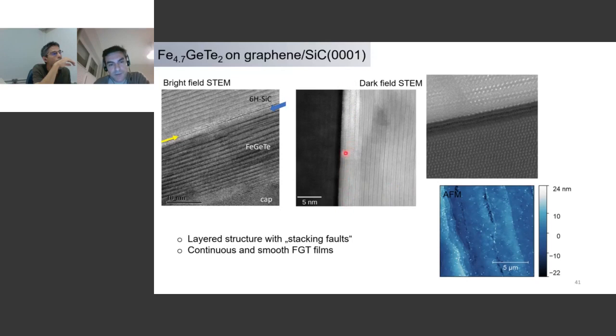We also see that you have some van der Waals gap that finish in the middle of a layer, and some stacking faults in general. That still shows there is a lot of improvement in terms of crystal quality here. But the nice thing is, looking at another dark field example here, you can see the graphene layers, and they are immediately followed by the FGT, the ferromagnetic layers on top. And you have a sharp interface between the 2D materials, and the film is relatively smooth. But again, you have these problems close to bilayer areas where you have a kind of non-uniform nucleation.